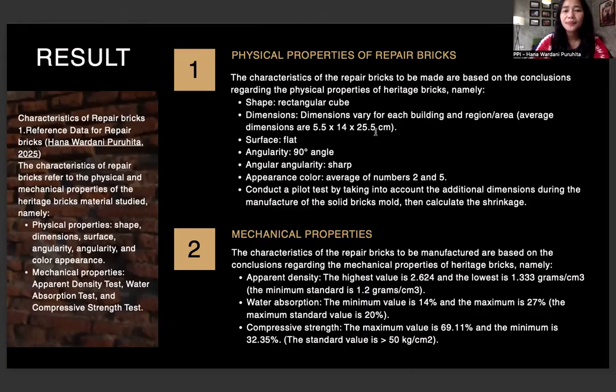Average dimensions are 5.5, 14, 25.5 centimeters. The surface is flat. Angularity is a 90 degrees angle. Angularity is sharp. Appearance color is the average of number 2 and 5, and I will give the coloring number, and then conduct a pilot test by taking into account the additional dimension during the manufacture of the solid bricks mold, then calculate the shrinkage rate. The second is mechanical properties.